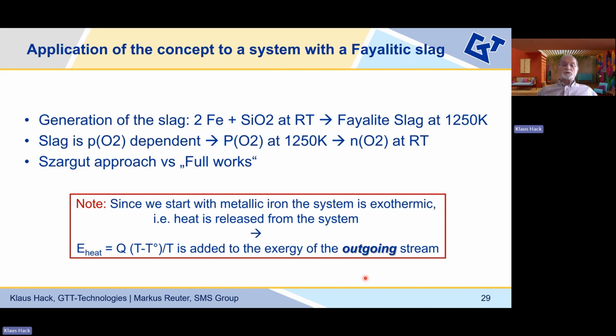So that is a step which needs to be taken into account in order to really get a full picture, because here the starting situation is that we have metallic iron, but we already have silica. In the end, we want to have a completely oxidized system, and that means, of course, there is reaction of the iron and the oxygen, which is exothermic, and that means in the end heat is released from the system, and therefore our exergy for the heat is to be applied, and it has to be added to the outgoing stream rather than the ingoing stream.